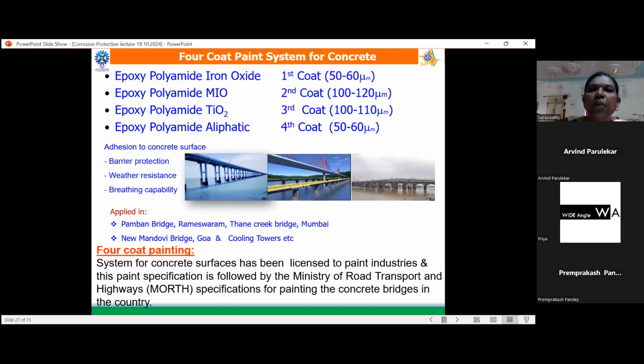The 4-coat system, which was developed and implemented in the Pamban Bridge, has been implemented in some other bridges like Thane Creek Bridge, New Mandovi Bridge, and cooling towers, wherever they are located very near to the sea or surrounded by an industrial environment. This 4-coat system contains epoxy polyamide iron oxide, epoxy polyamide MIO, epoxy polyamide TiO2, and epoxy polyamide aliphatic. Each and every coat has its own significance. The first coat gives adhesion to the concrete surface, the second coat gives barrier protection, the third coat, since it contains TiO2, is highly weather resistant and has breathing capability, and the aliphatic polyamide is highly UV resistant.